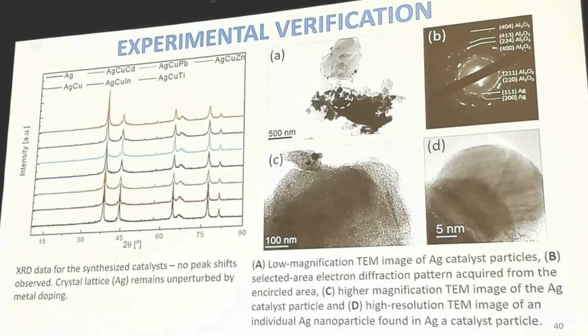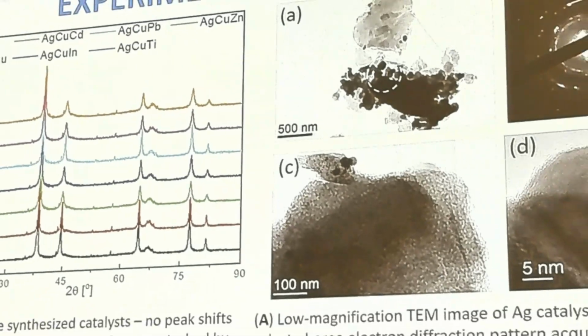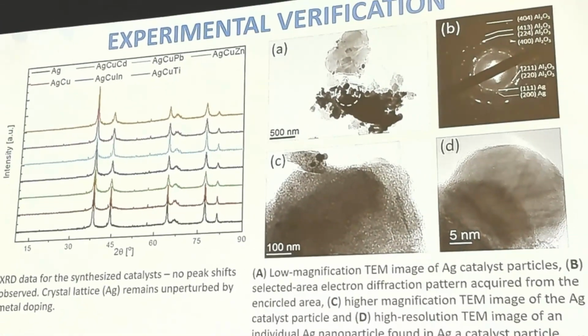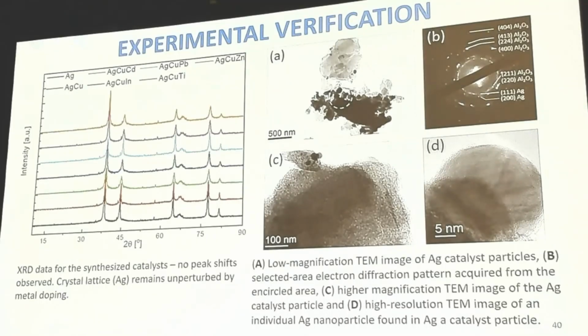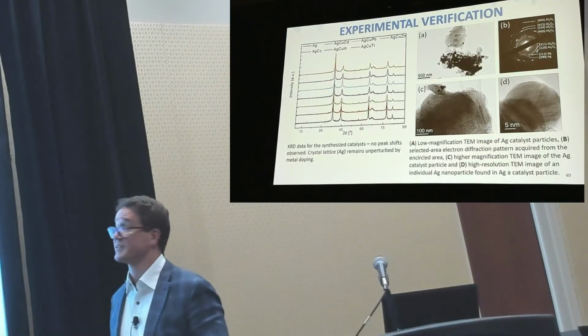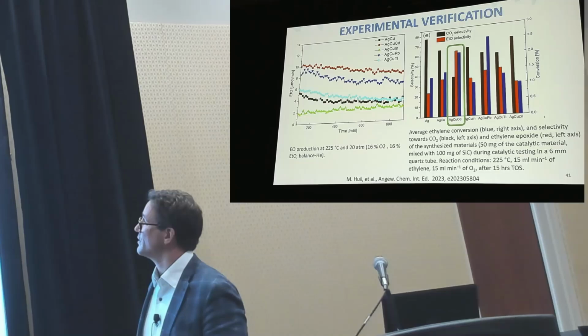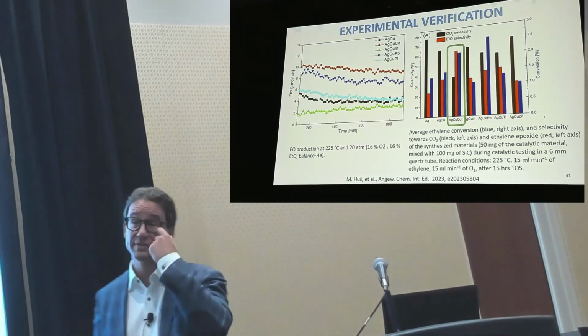That's important, of course, when we compare, since we know that we are missing the oxide formation. So when we go to the lab, we want to compare to the more metallic form of particles. And you can form these. You can also look at signs. When they go in, these extra metals are at such a low limit that we don't expect them to accumulate, and we don't see any traces of the alloy metals as such. So they are hopefully dispersed throughout the silver particle.